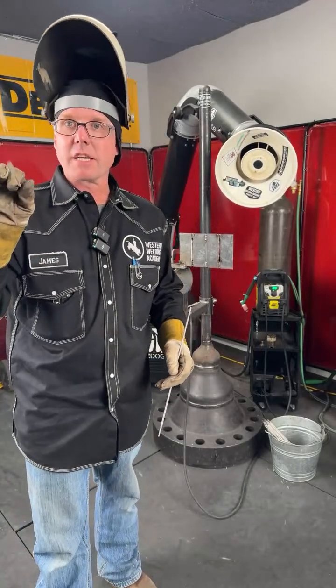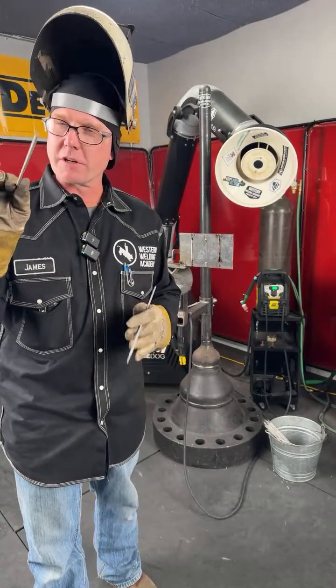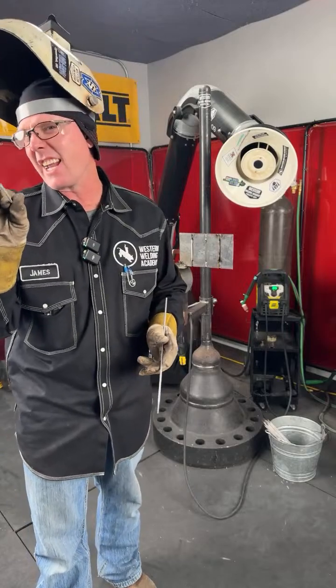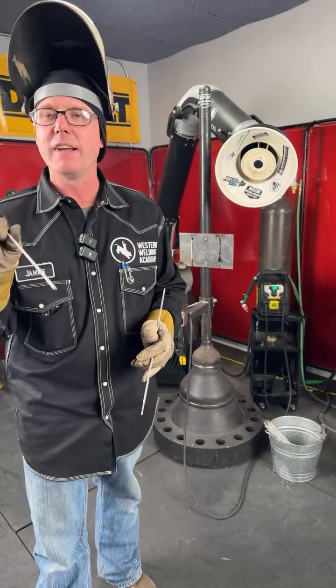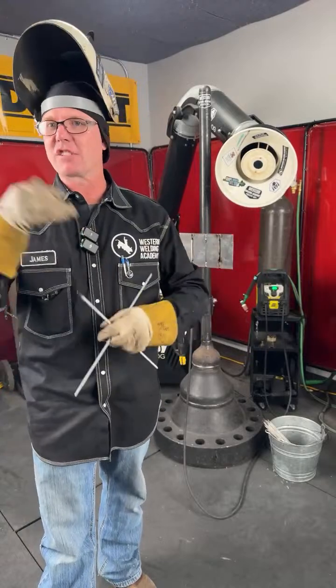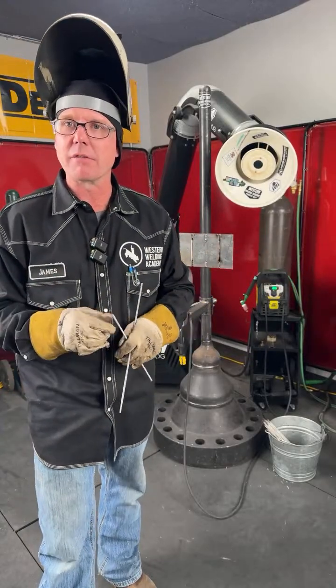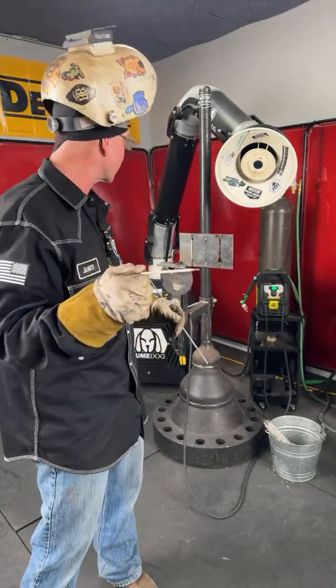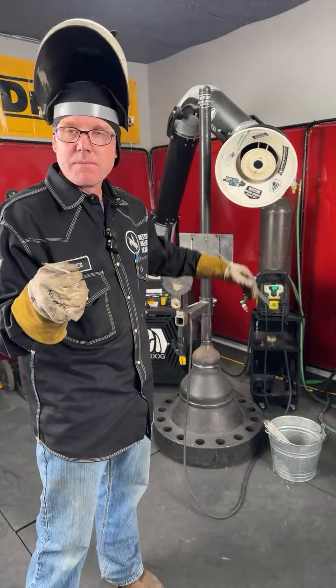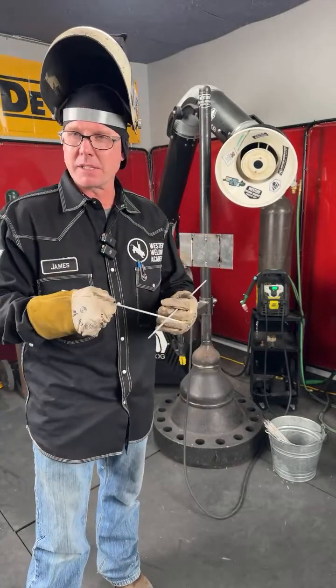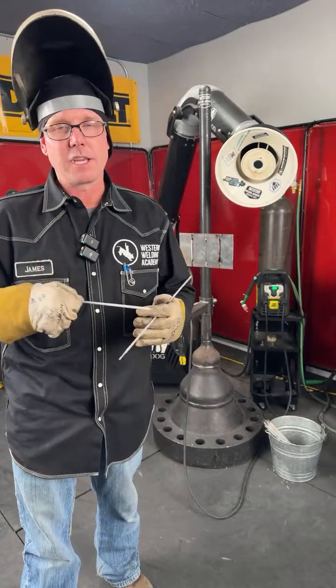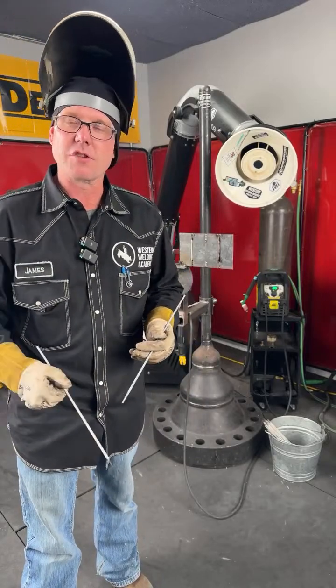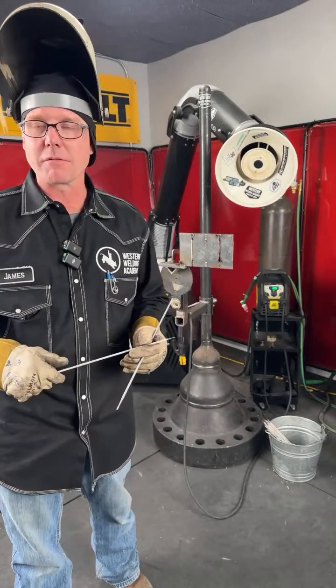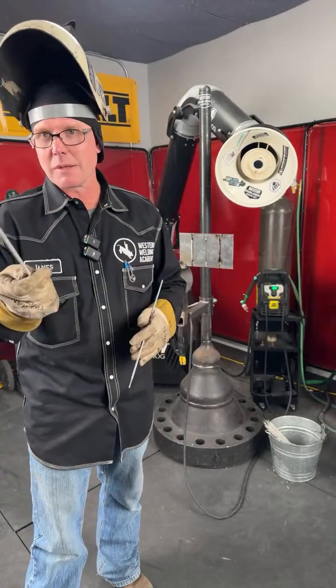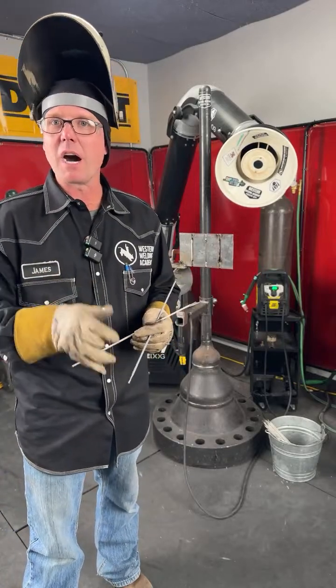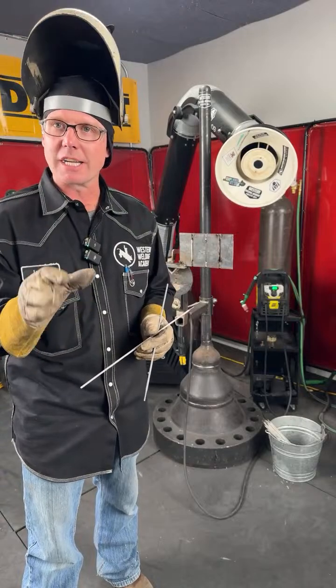With 60-10 1/8 inch, a good starting point, if you're just running beads on plate, start out with like 90, 95 amps. Run it kind of hot, and then when you see a lot of real bad spatter, start ramping it down from there. It's going to depend on the machine. This ESAB we're using, about 85 amps is a good spot for my 60-10. We've got some Lincolns in the shop that you probably run at 100, 105 for 60-10, so it's going to depend on the machine, but start out a little bit hot with your 60-10. That'll help you learn how to get the rod started.